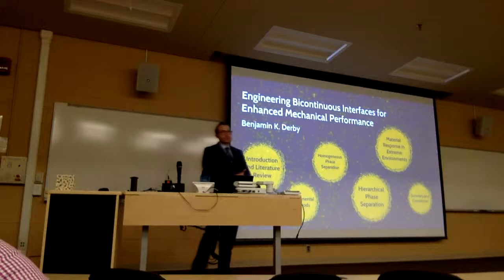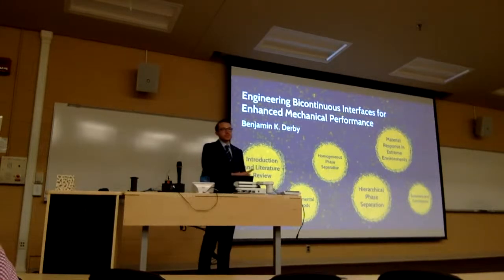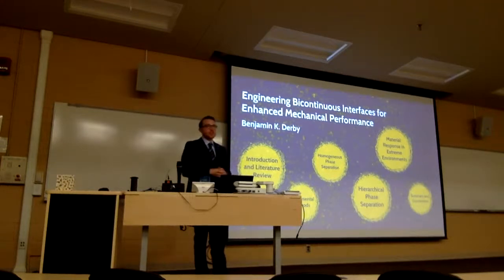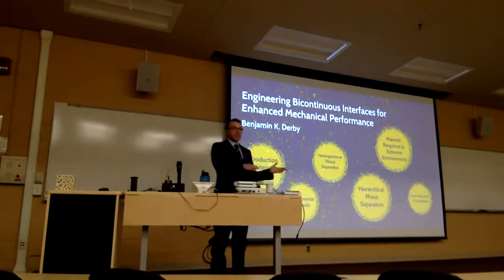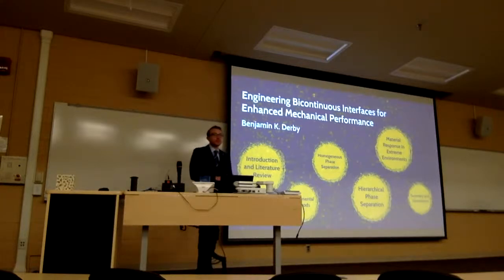Speaking of other systems, you noted that the hierarchical structure was present in copper-moly. Would you predict it for any of the other systems, and how would you know? That's a great question. We've experimented with copper-iron, which is also an immiscible system. Our initial results suggest that it behaves very similarly, but in a different set of deposition conditions. Depending on how insoluble the system is, and where you see the immiscibility, you can deposit those same morphologies. Does that answer your question? Sure, but of the hierarchical structure specifically? Oh, the hierarchical structures. What we predict is that, as in the copper-moly case, under certain conditions, if the mobility or surface diffusion length difference between the two constituents is large, we might be able to see that hierarchical morphology. We actually published work with copper-tantalum that shows a very similar morphology progression, which has a very disparate mobility between the constituents.